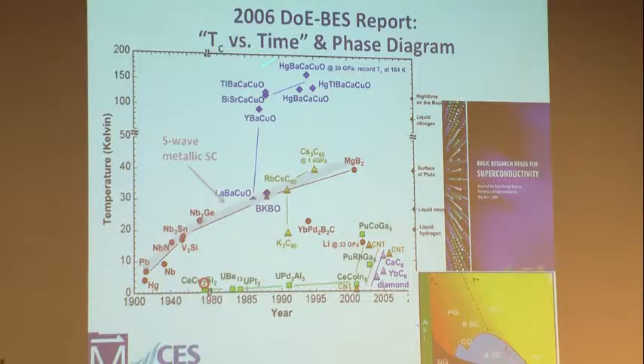Here's just a bunch of the high TC cuprates. I have the iron-based ones on the next one. None of those are electron-phonon-coupled superconductors. And they all show pretty much the same kind of phase diagram, which I've mentioned before. This is the one taken out of that report. And what we have in this phase diagram is temperature versus pressure or doping. Here's the superconducting dome, under which is superconducting.